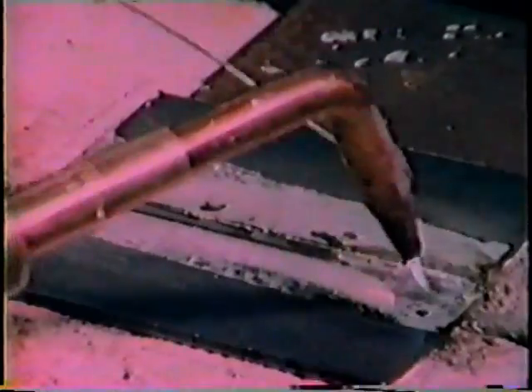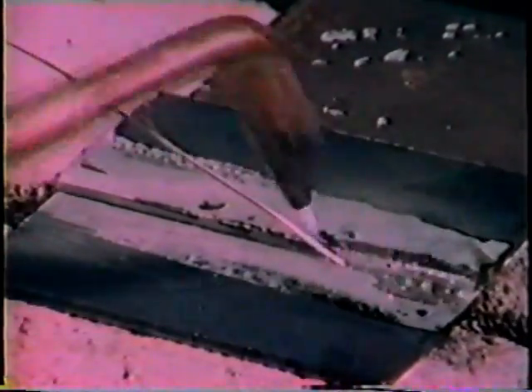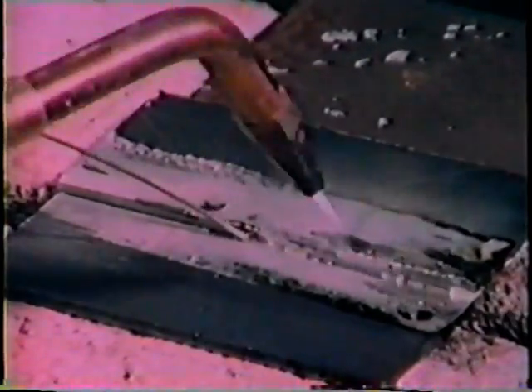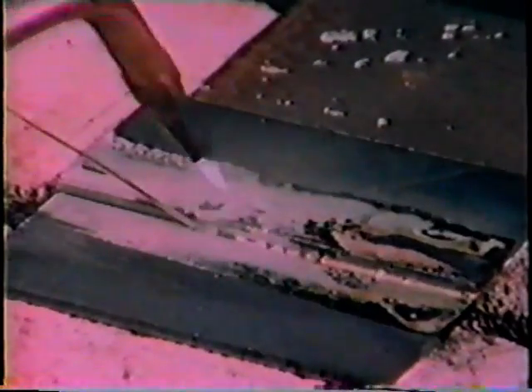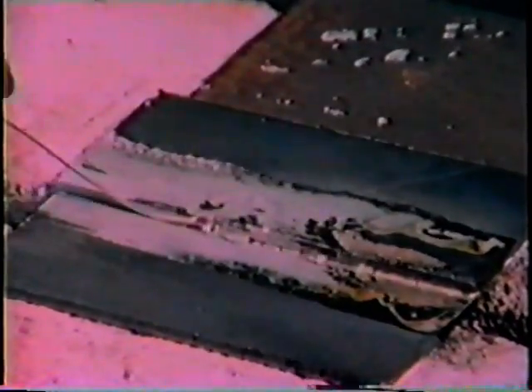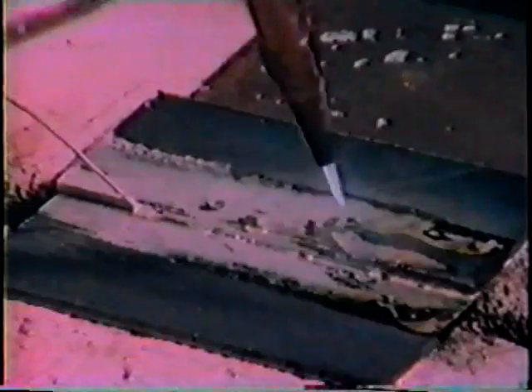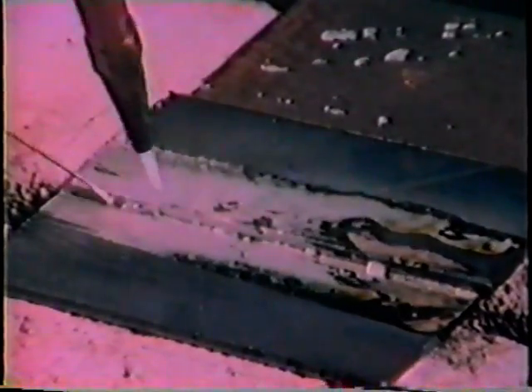Checking to see that the torch flame is in a neutral or slightly carburizing setting, feed the brazing alloy into the joint until the silver solder no longer disappears. While no bead buildup is recommended, complete penetration of the joint must be obtained. Again, remember that if the silver alloy smokes, too much heat is being applied to the joint.